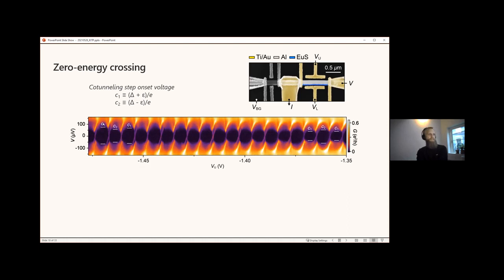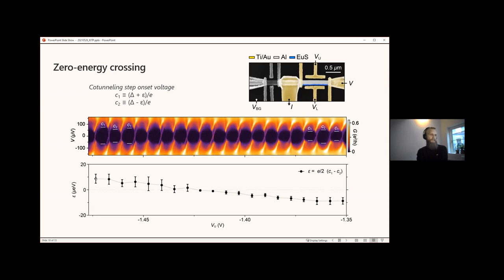Using these energies, you can see that if we index each Coulomb diamond as 1, 2, 1, 2, we see that on the left side of the graph the Coulomb diamonds with index 1 are larger, whereas they become smaller on the right side. Now, if we extract the subgap state energy from this data, we get the following picture. We see that the subgap state energy crosses zero, and therefore C1 becomes smaller than C2. In addition, we can employ the method introduced in the beginning of the talk, namely the peak spacing difference. Comparing those two methods, we find that the extracted subgap state energy agrees well between the two.